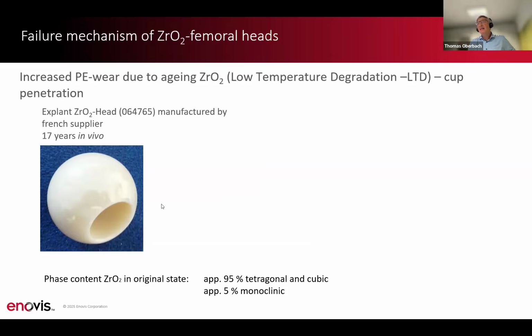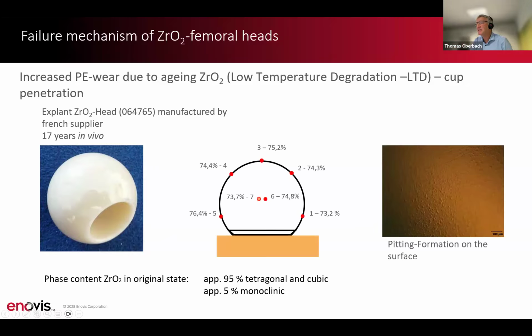To explain it a little, here we had the possibility to investigate an explanted zirconia head from a French manufacturer, and this head was 17 years in vivo in the patient. And normally, when such a zirconia head is produced and before implantation, the tetragonal and cubic phase content is approximately 95%, and the monoclinic phase content is approximately 5%. And we investigated this head, and we found on the surface that the monoclinic phase content increased after the 17 years up to more than 70%.